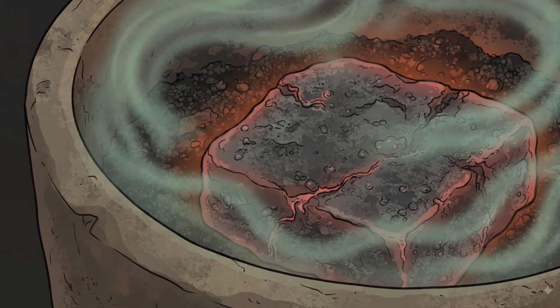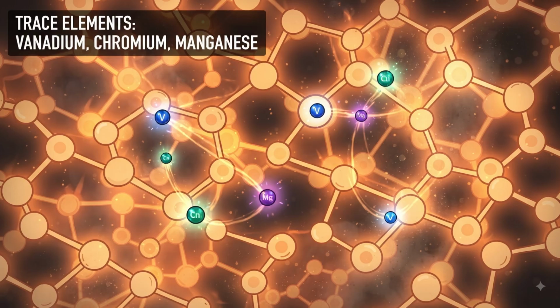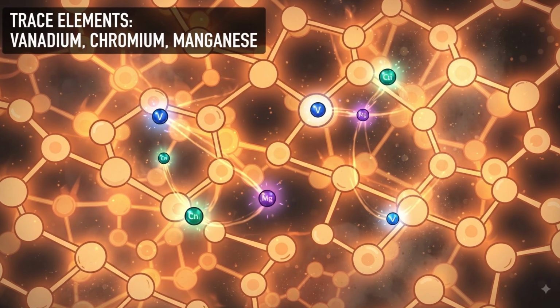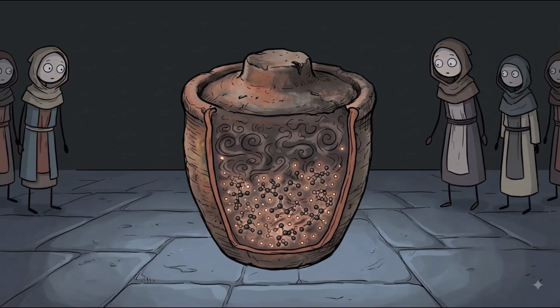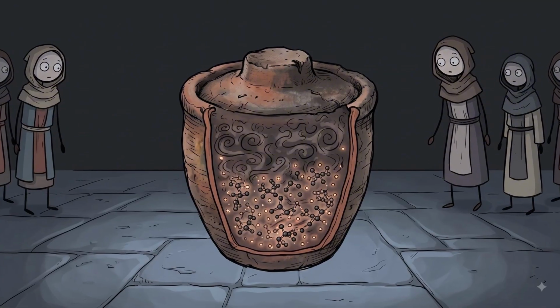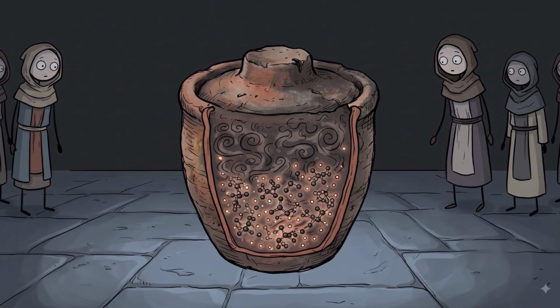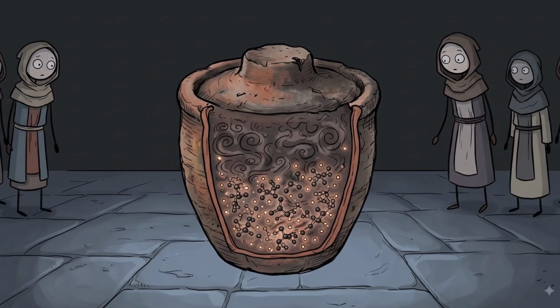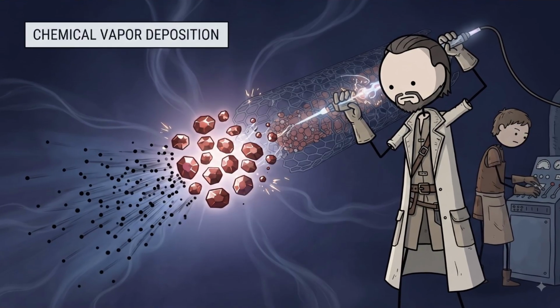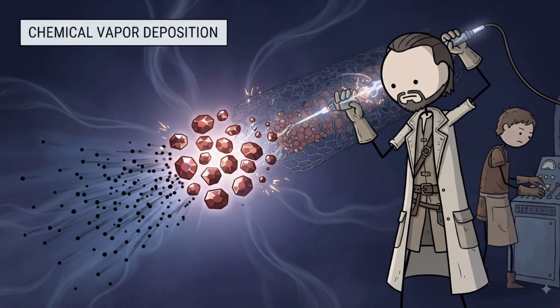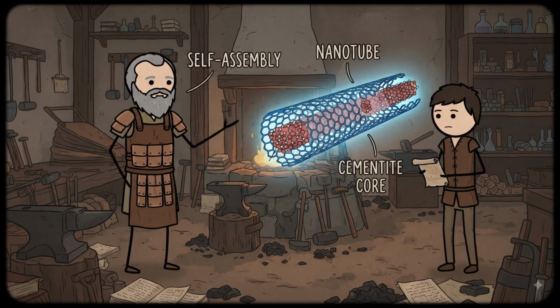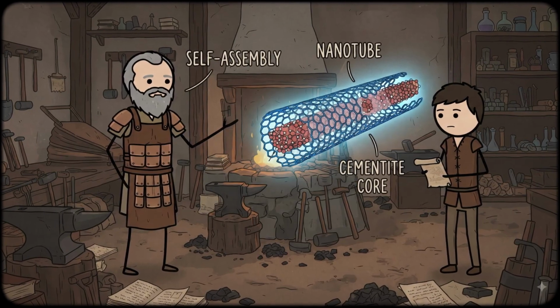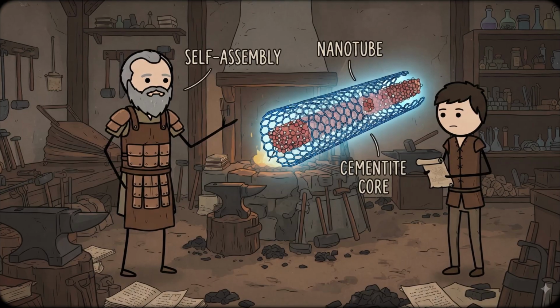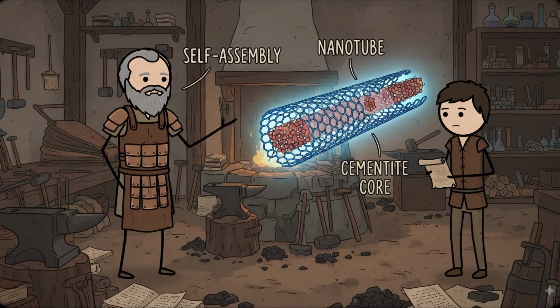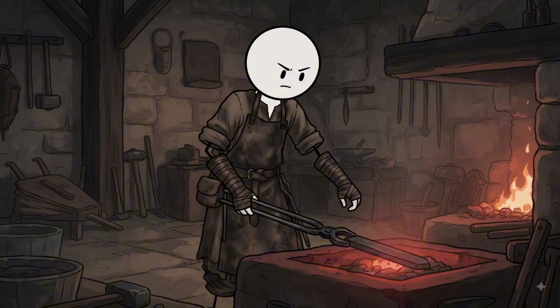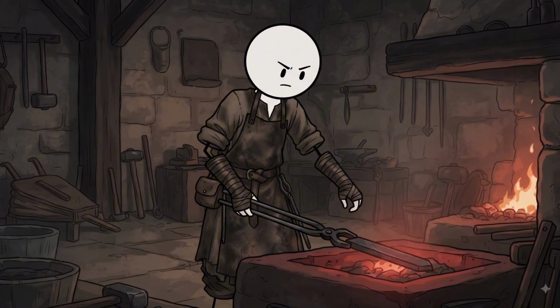This is where the invisible magic happened. Because the crucible was sealed, the burning organic material created a highly pressurized, carbon-rich gas. The specific wootz iron ore from India contained microscopic trace elements of transition metals, specifically vanadium, chromium, and manganese. Inside the blazing heat of the crucible, these trace elements acted as chemical catalysts. As the steel cooled over several days, the carbon gas was forced to bond around the trace elements, initiating a process known today as chemical vapor deposition.